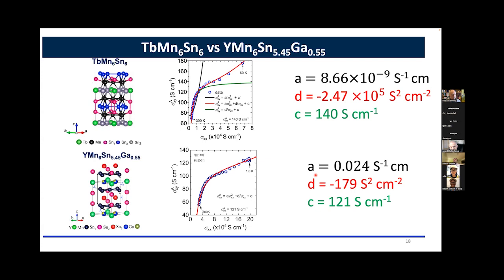This system should not have as much of a fluctuation as in terbium manganese six tin six. And you can see that the value of D that was 10 to the power 5 in this case comes down to be just about 180. It's a much reduced part. So this term is very, very weak in this system. There may be some fluctuations in the system, but not as dramatic as in terbium manganese six tin six.